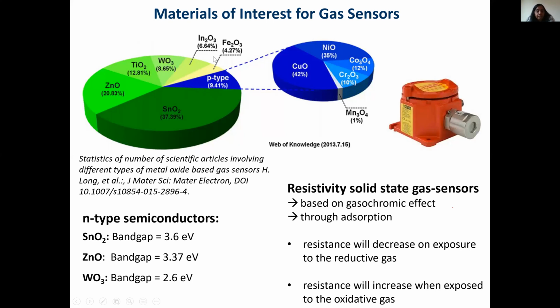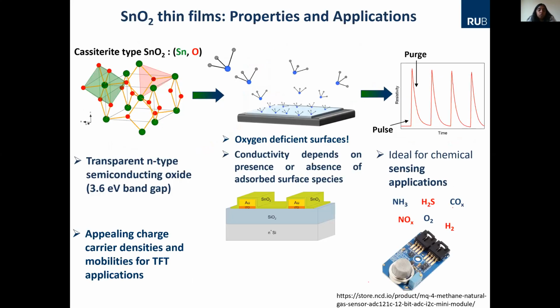And this is where, again, we would like to grow these materials. They are available as bulk. The standard sensors are bulk or thin films. But when you want to have large areas, thin materials with better functionalities, then maybe CVD or ALD could be a choice. So just to give a background on tin oxide, it has the cassiterite type structure. You have the tin as the green balls here and oxygen as the red ones. Here you see the packing, and this material has a certain oxygen-deficient surface, and this is where the conductivity can vary depending upon the presence or absence of the adsorbed species.